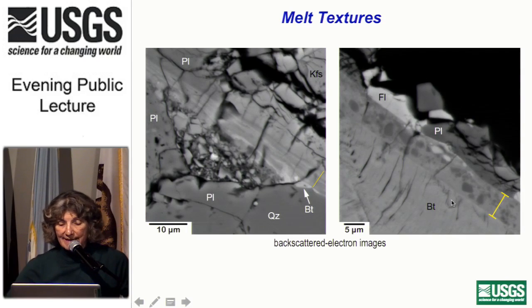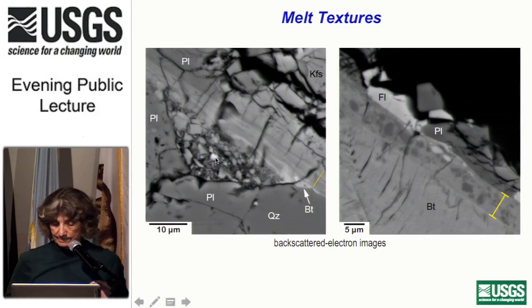Over on the right, you can see very well-defined boundaries of the melt layer. In this location here, there were a lot of mineral fragments that were caught up in the melt, and these have rather rounded outlines. This may be a product of melting-induced wear on the grains. These rounded shapes are rather different from the very angular shapes of the broken-up mineral fragments that weren't in contact with melt.